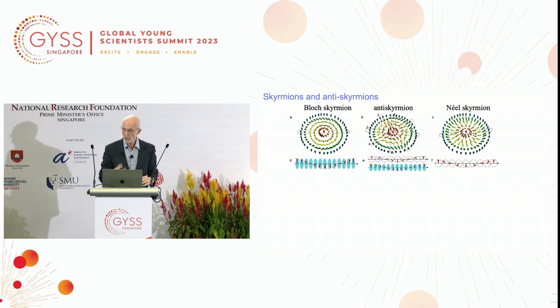And it turns out that with theoretical predictions, we could see another object called an antiskyrmion, where in this case, because of the symmetry of the crystal lattice, this Dzyaloshinskii-Moriya vector exchange has a different sign of its vector components as you move around in the lattice structure if you have the right symmetry. And there was a prediction you could see something called an antiskyrmion, where the boundary alternates between Bloch-like domain walls and Néel-type domain walls. And we were the first to discover this.